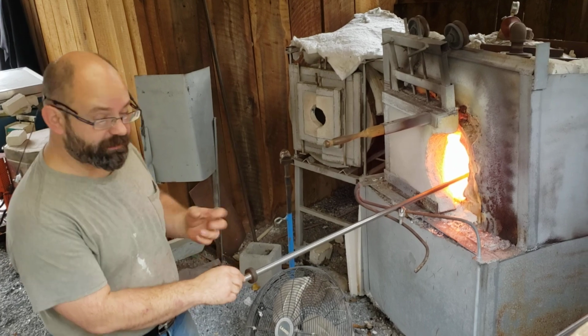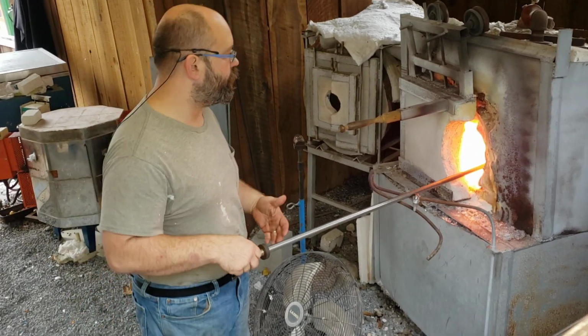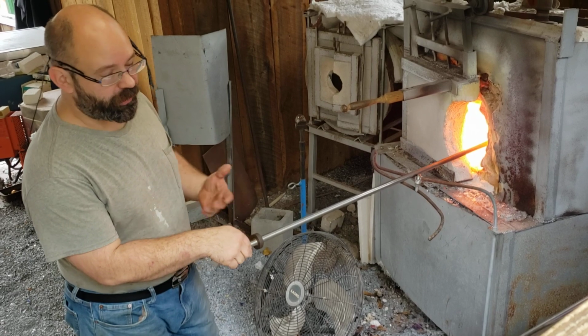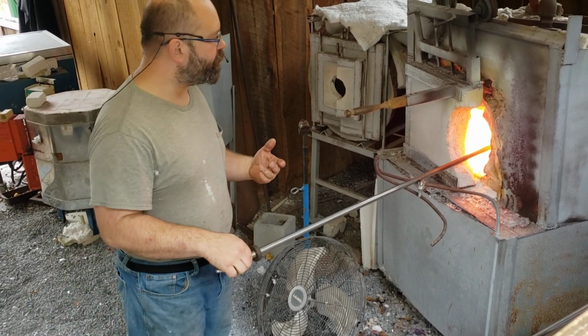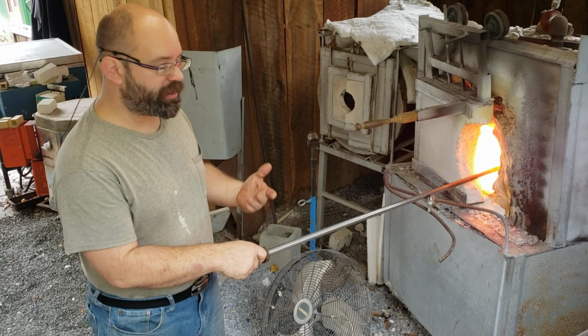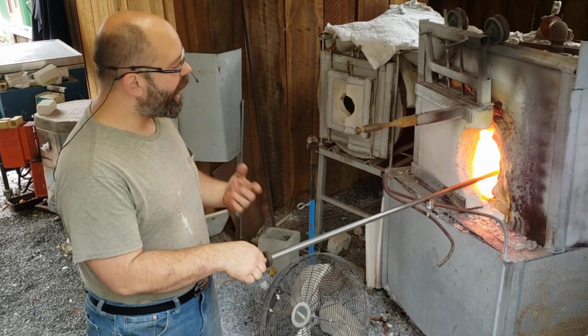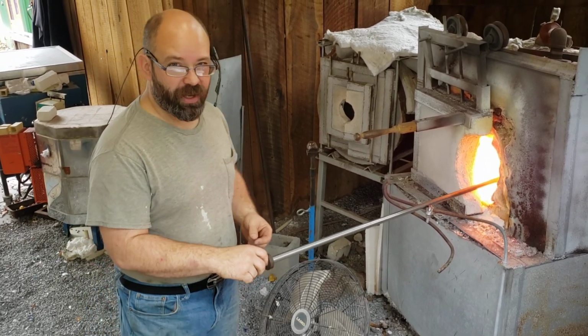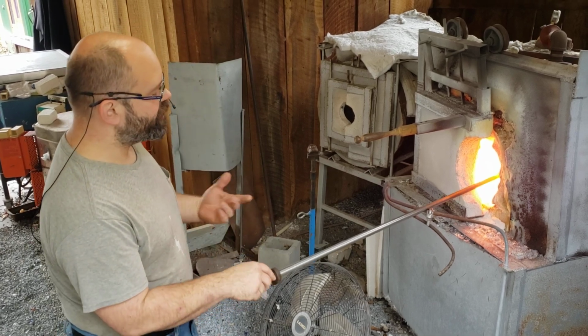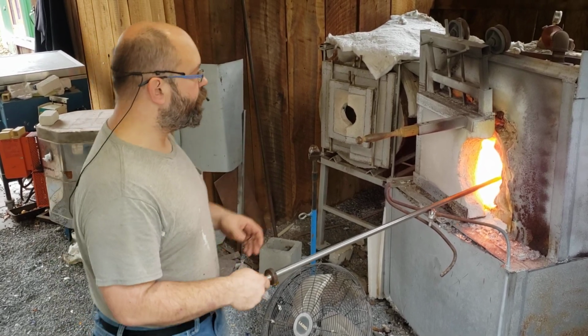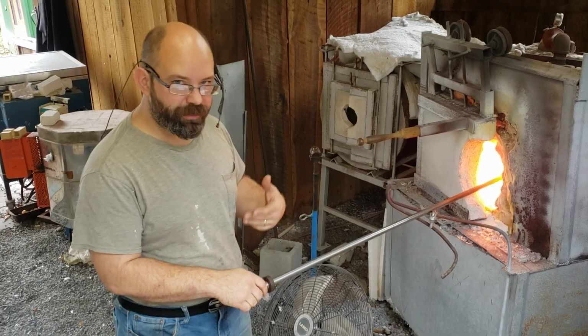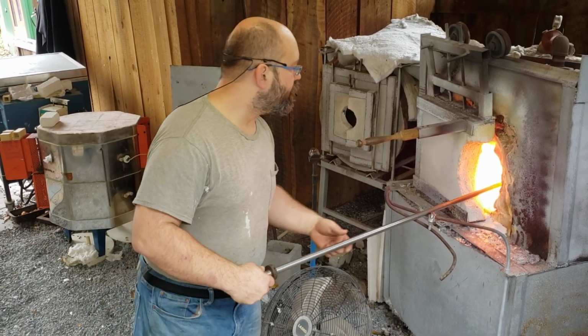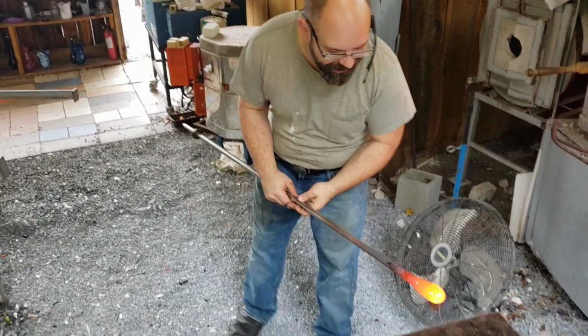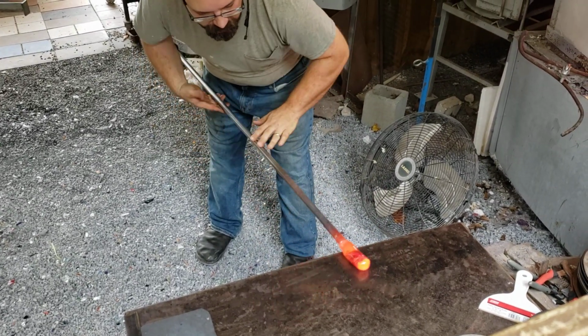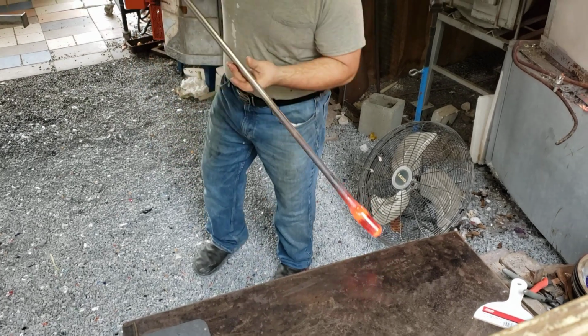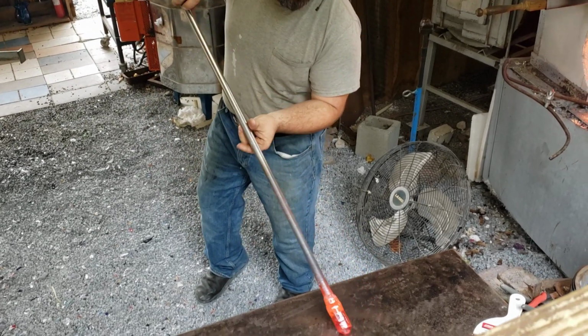Now, I personally am a fan of small air bubbles. I like the way they look. I think they give character to a piece, but large ones can be a structural issue. If you have real large air bubbles, what ends up happening is they can get too close to the surface, and then they can blister and pop after the piece is finished, and you get little sharp spots on the surface of your glass that mar its appearance and make it unsafe to use. We don't want that, so I'm going to melt the texture away to keep the movement in the color. Most of that has melted away on its own, and I can press out what hasn't melted on this table. Nice, smooth, controlled movements are key.